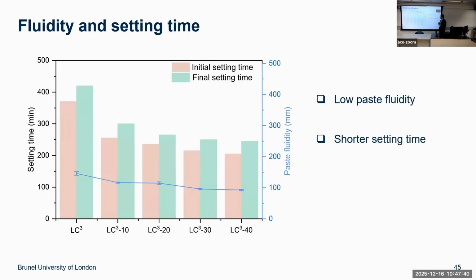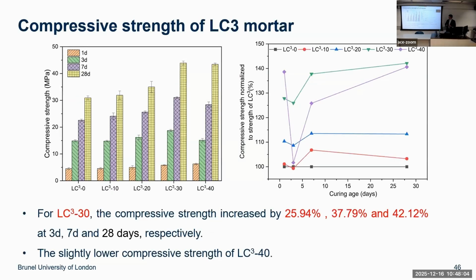Okay, but we found that because of the injection, there is less fluidity. Basically the workability is reduced. It becomes more sticky. That's why we need some kind of superplasticizer later on, and the setting time is shorter because the hydration moves earlier forward. Both the setting phase and the remaining phase, and sometimes it's a flash setting, which could be a problem.